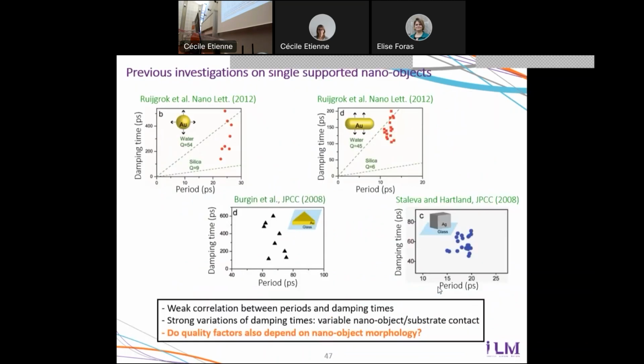So let's start with previous investigations of single supported nano-objects. Here you have a summary of a few previous experiments. Damping time as a function of period. A straight line like this corresponds to a constant quality factor. You can see several things on these different plots. Usually the quality factors are not very high, a few tens typically. Also, typically the data is elongated vertically. It means that even if you work with different nano-objects which have approximately the same size and therefore the same frequency, they will have very large differences in quality factors, which was initially ascribed to the fact that when a nanoparticle is deposited on a solid surface, the quality of the contact between the particle and the surface may be different from one nanoparticle to another.